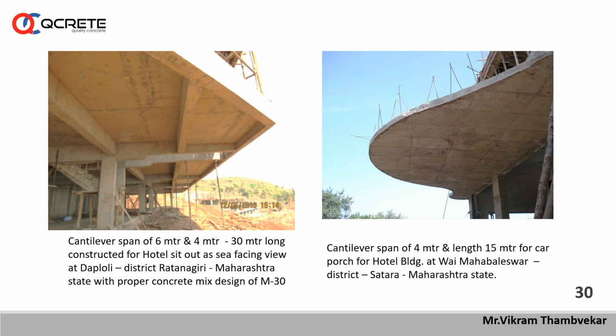It's very sleek. And we used fresh concrete at site with local material, local laborers, with an ordinary drum type mixer. Here I want to explain that making fresh concrete in a proper proportion, in a proper way, with proper control of the water cement ratio is very important. Then only can we get a good result for such larger span members or larger span structures.